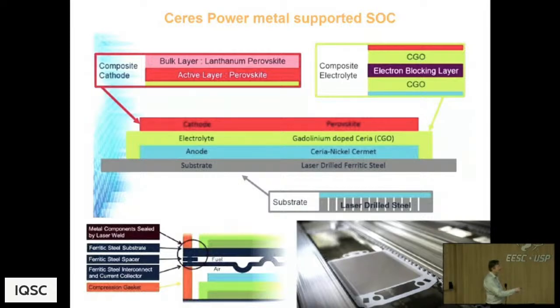It becomes mixed conducting in fuel environments, even at 600 C. So they put an unspecified electron blocking layer on there, which blocks any mixed conductivity, without which you can't really get a high efficiency device. And then a cathode, and they don't tell you what the cathode is. But it's a perovskite. So that's the material set.